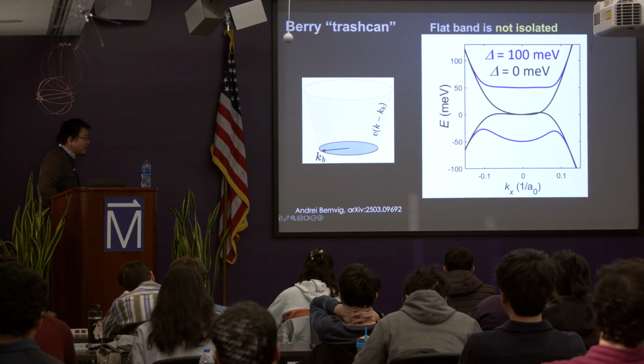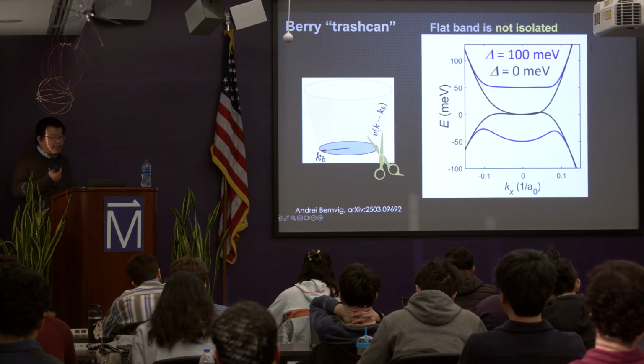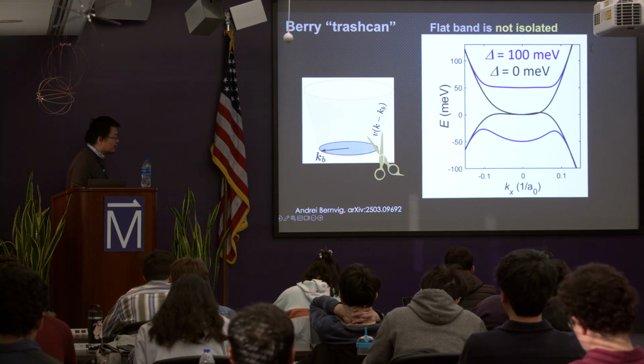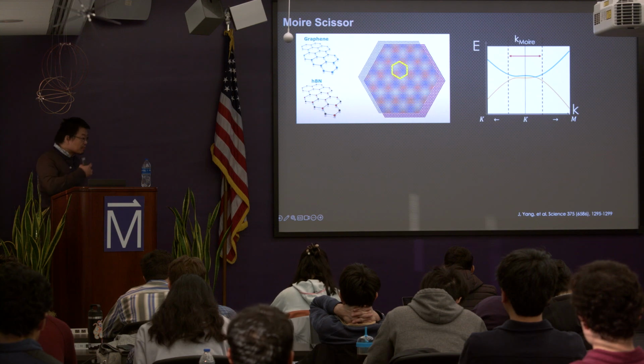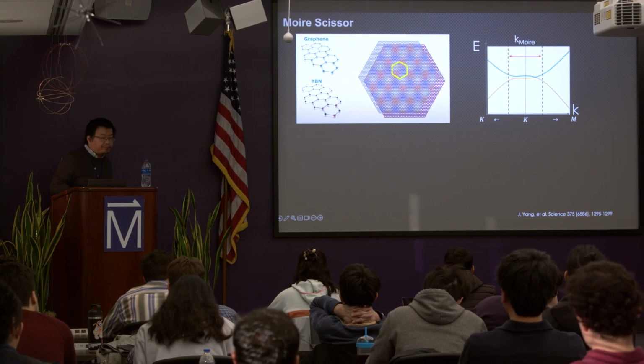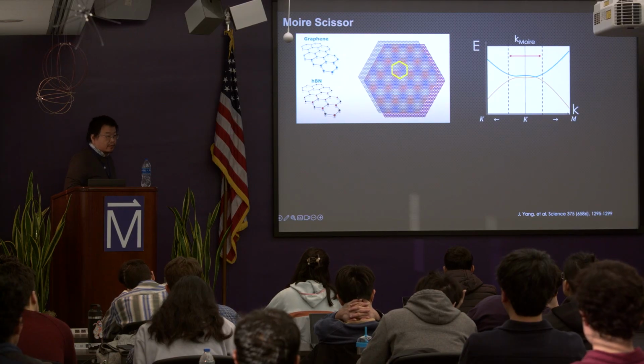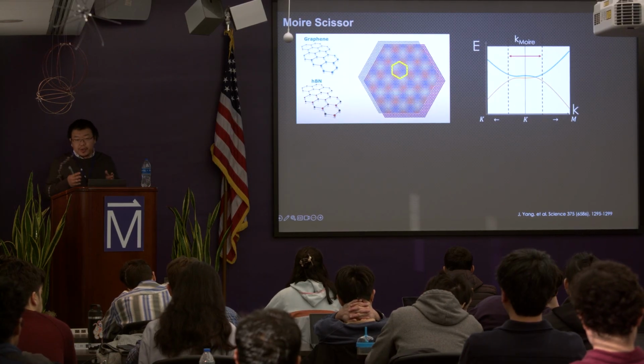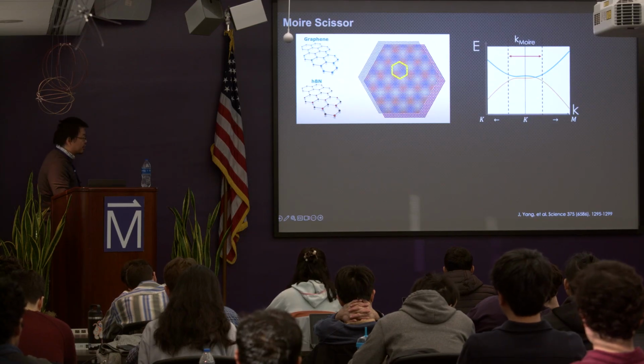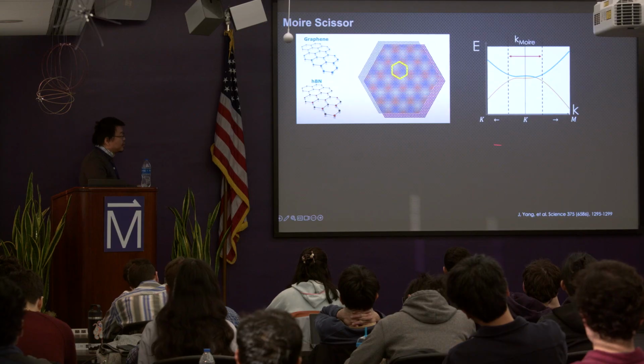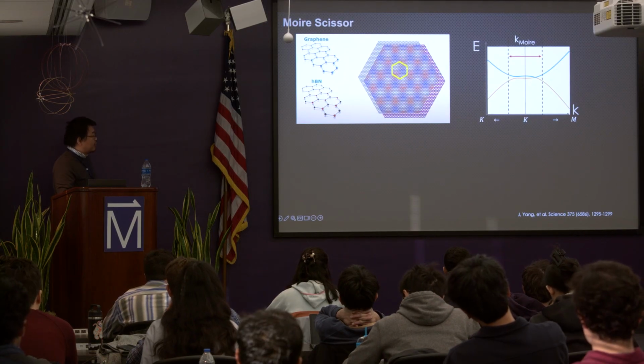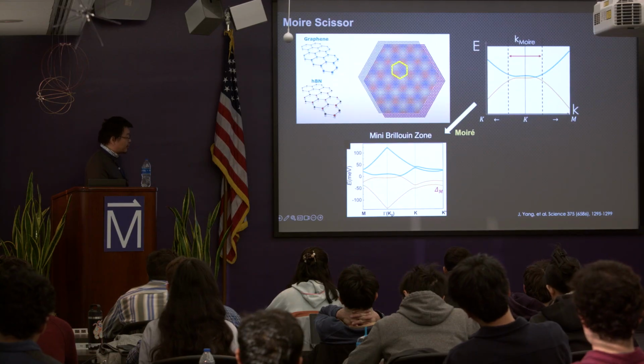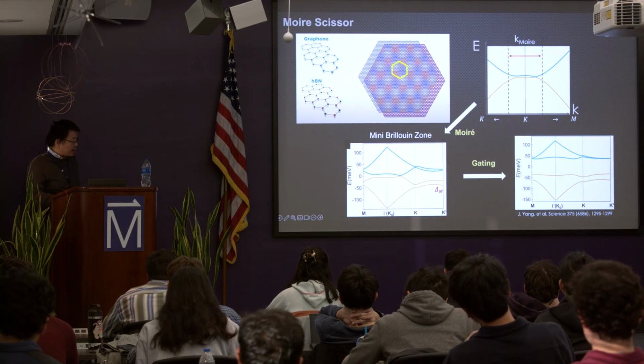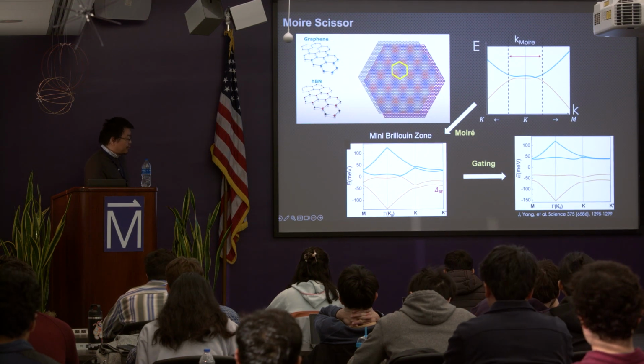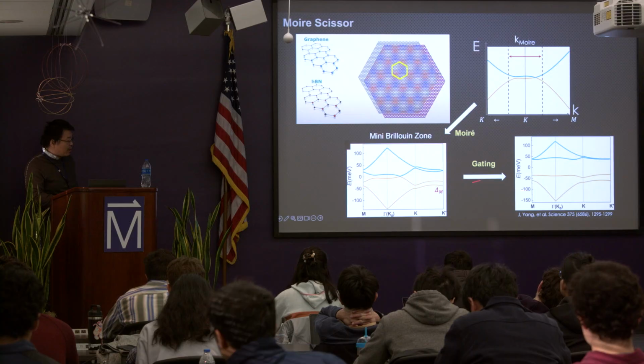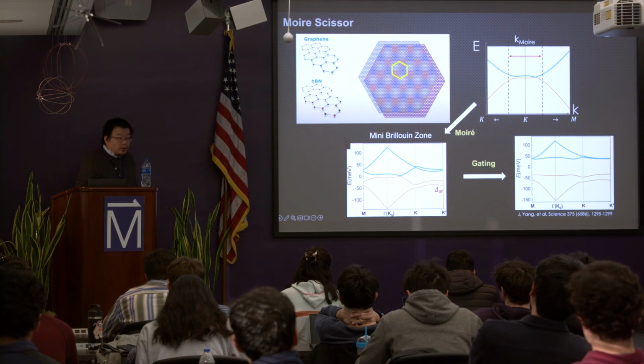So you need to probably find some way, like a scissor, that can cut off the bottom of the trash can. So the scissor is a moire. If you form a moire potential with, for example, hBN, then you truncate your Brillouin zone, right? So you can select your moire wavelength, and then you basically select the size of your Brillouin zone and how much you cut off. For example, this is a band structure of trilayer graphene, and if I add a moire potential with hBN, you basically have the band folding. And then if you add an out-of-plane electric field, you're further squeezing the bandwidth. It's not perfect, but it looks somewhat flat, right?